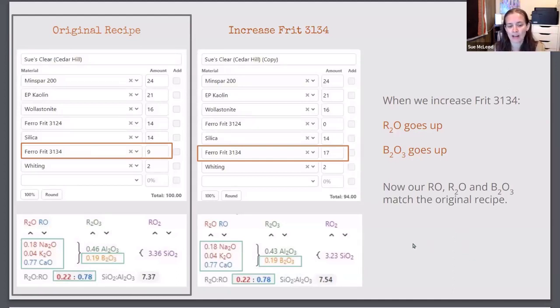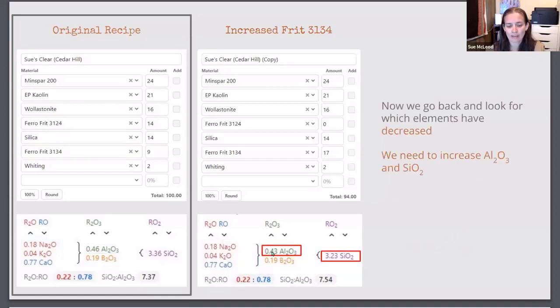So now I move on to, okay, what else has gone down? We've got the alumina has gone down. So it's 0.46 here, 0.43, and the silica has also gone down. So I'm going to say, okay, what do I need to increase the alumina? I always leave silica for last because silica is one of the only materials where you can just add straight up silica. Alumina, I have to add clay, which contains both silica and alumina.